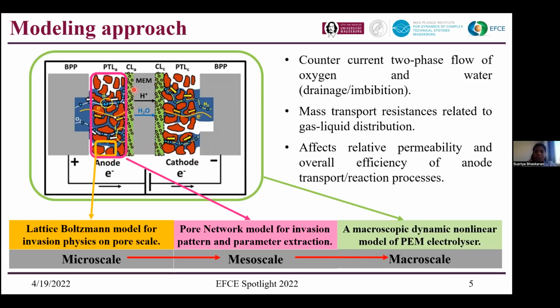With this idea about the anode porous transport layer, we would be dealing with this problem at three levels, starting from the micro scale, then moving to the mesoscale and to the macro scale. At the micro scale, we apply the Lattice-Boltzmann model to understand the invasion physics at the pore scale. Then we consider a bigger size of the porous structure, where we deal with the pore network model. Again, we see the invasion pattern of oxygen as well as water, and we also extract the parameters for the macro scale model. In the macro scale, we consider the entire system, so we get an overall idea about the efficiency once we modify this anodic porous transport layer.